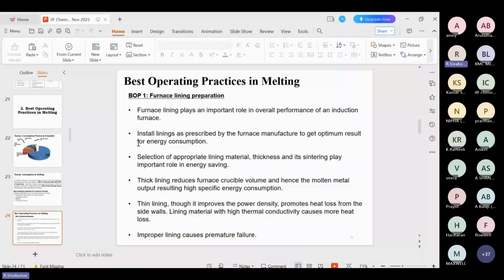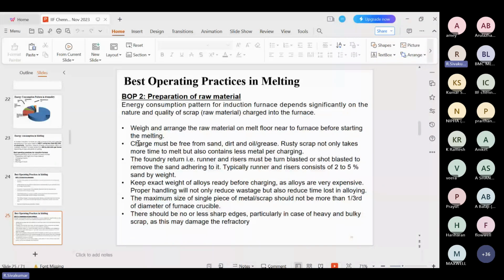And preparation of raw material. The energy consumption pattern of the induction furnace also depends purely on the quality of scrap fed into the furnace. So weigh and arrange the raw material on the melt floor near the furnace before starting the melting. I think most of the foundry units are following this best practice in the melting area. Next, the campaign metal is to be weighed and kept separately near the furnace for the next batch.